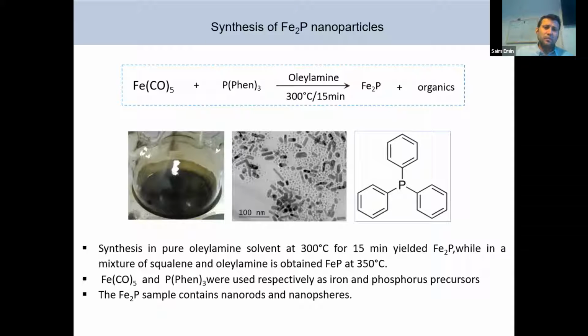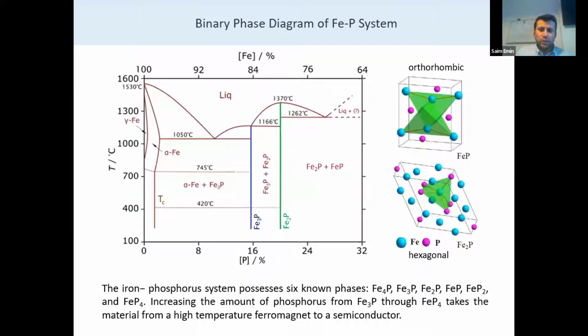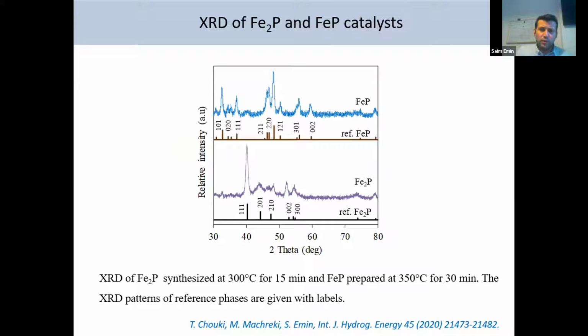The synthesis of metal phosphides was done using iron pentacarbonyl precursor in the presence of a molecule called triphenylphosphine. This molecule, as a phosphorus source, is quite cheap compared to the other precursors used in the literature. At 300 and 350, we can grow different phases. At 300, we can grow Fe2P, and at 350, we can grow FeP. So by increasing the amount of phosphorus, we can grow a phase which is rich in phosphorus. Here is the diffraction pattern of these two phases. We have them in pure form, both materials, and they correspond perfectly to the database references.